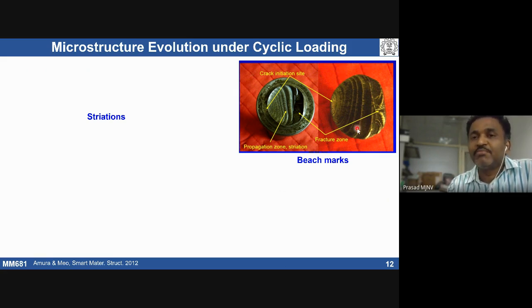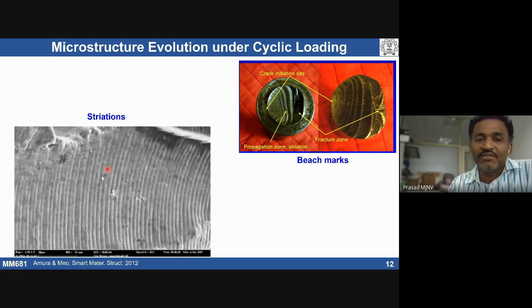If I go to SEM level fractography, we do see the formation, within a grain, of this kind of marks. These marks are called striations. Each striation, from one to the next, indicates that the crack has propagated for each cycle. We already learned that the crack front moves for each cycle. So within a grain, by looking at how many striations there are, people can say how many cycles the material has experienced for the crack to propagate. So these are the microstructural features which indicate that the material or component failed due to cyclic loading conditions.